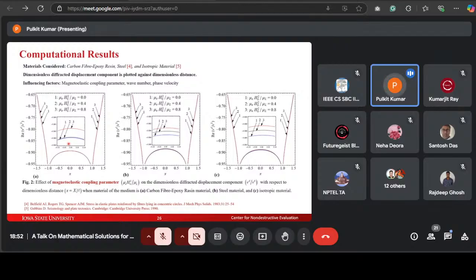So the figure shows that as the coupling effect increases, with values 0, 0.4 and 0.8, the diffracted displacement also increases, both inside and outside of the strip. This happens in all three materials: carbon fiber epoxy resin, steel, and the isotropic material. You can see the maximum energy is at the center and decreases towards the edges.